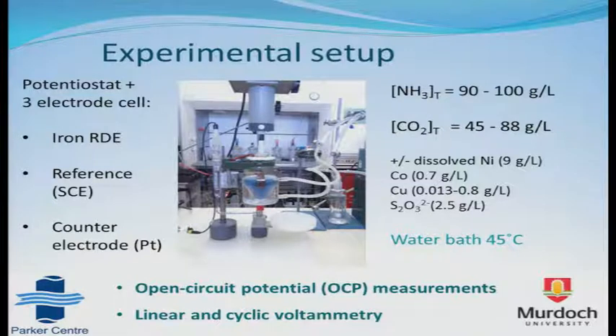The main measurements I conducted with this setup are open circuit potential measurements, which are just looking at the real situation. I'm not applying any current, I'm not doing anything particular to the iron. I'm just looking at its potential and monitoring it and seeing whether it's still actively dissolving, because the potential can tell me a lot about whether it is active or passive. But I also need to combine it with some voltammetric measurements in which I apply a potential and look at the current response, which can give me an insight into what reactions are taking place, whether the iron is active or passive, and what other species might be present at the interface.